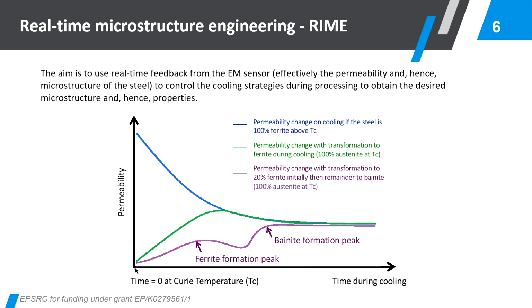Two things can change the magnetic permeability of the steel. One is its microstructure, and the other one is temperature. There's a famous temperature called the Curie temperature, because above it the steel loses its ferromagnetism. So everything is paramagnetic, and you see a very small signal from the sensor. However, if you have a steel product that has already transformed before this Curie point, which in steel is around 770, then during cooling you will all of a sudden get a very strong signal at the Curie point, because the material has already transformed.